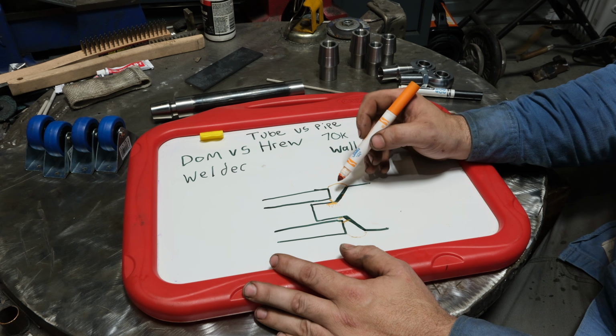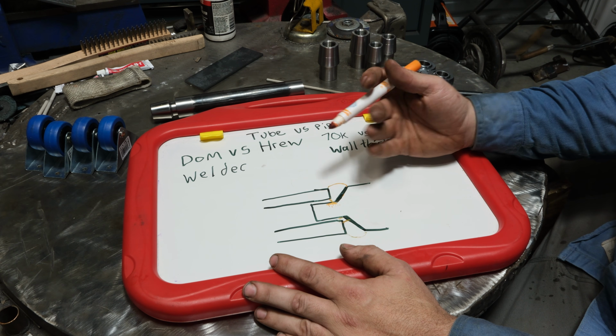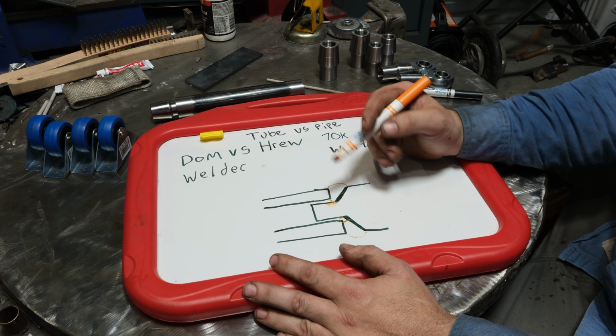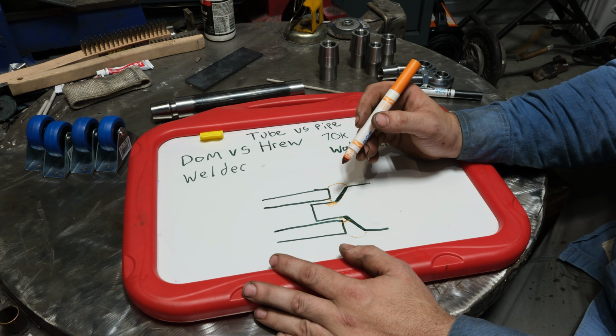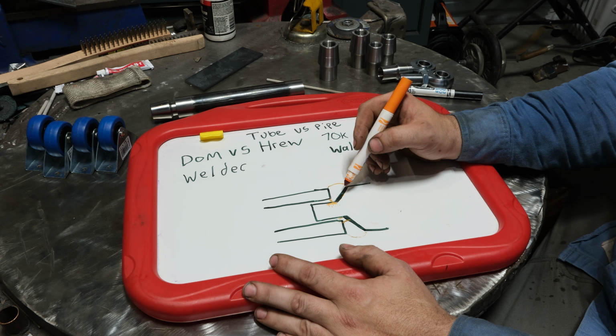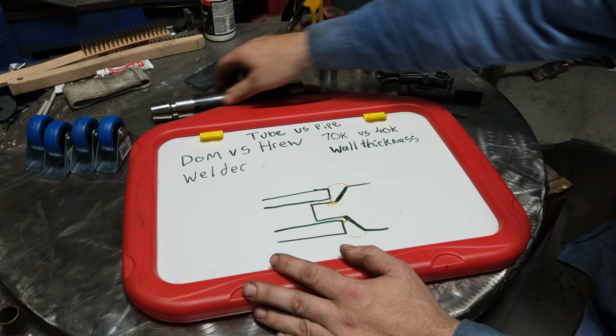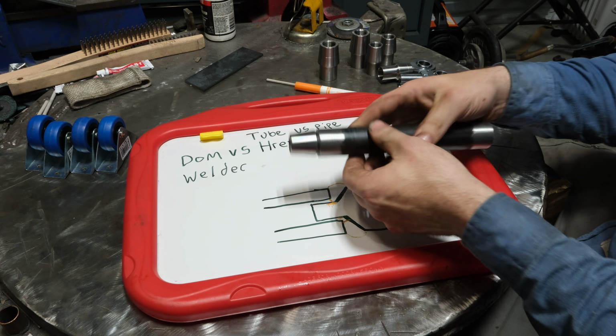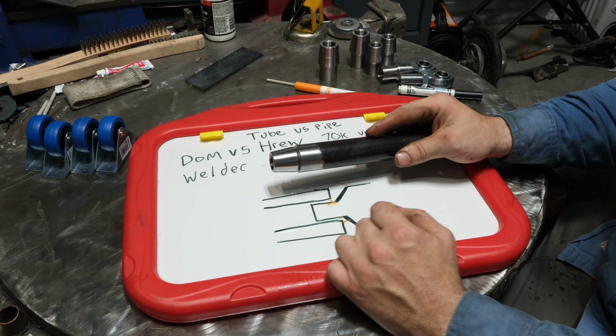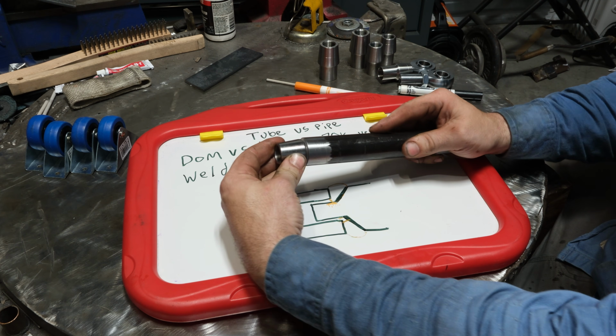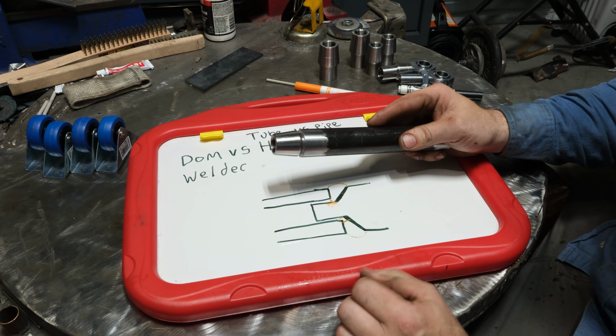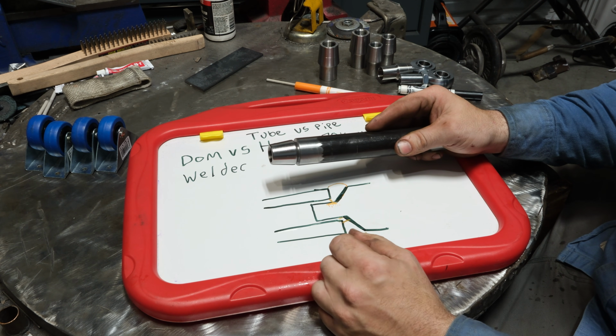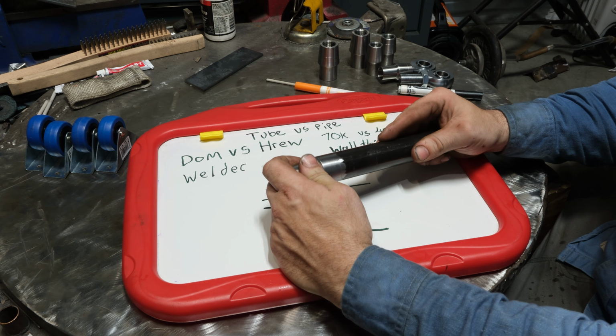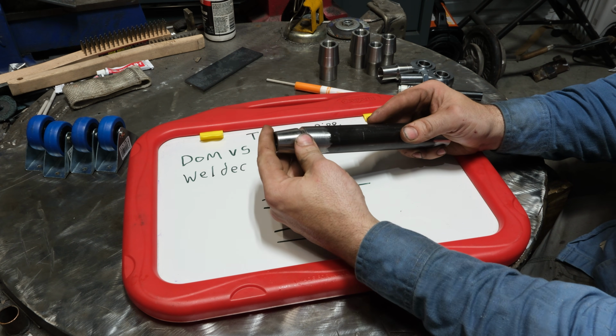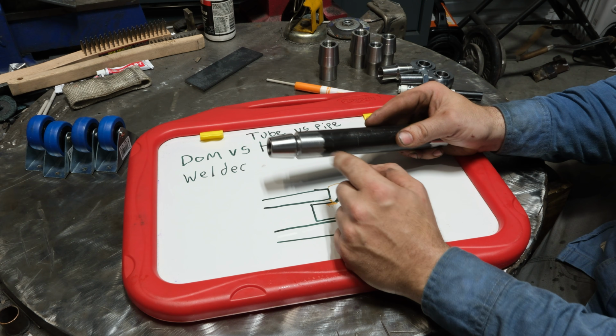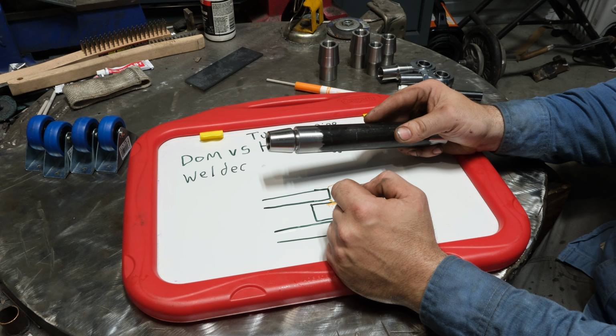Another thing that's pretty important about this, and again, this is my advice, you can choose to do what you want. I do not recommend tack welding and then welding over the tacks on this, and let me explain. The fitment of these inserts in this DOM tube, because this tube is held to such a tight tolerance, has absolutely no wiggle on it, okay? This is a very tight fit. Putting tack welds on this, regardless of where they are, and then welding over it is going to produce a lack of fusion at the tack welds.